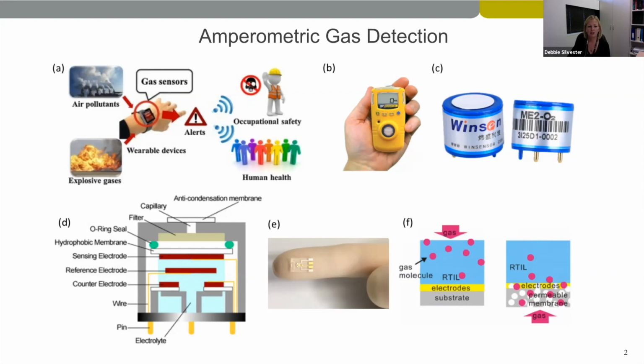So these kind of sensors are based on a 1950s design, and they're very widely used in industry, but they have a couple of drawbacks in that they typically use a fairly high amount of expensive platinum electrode material, so they're very hard to miniaturize, and they also have this liquid electrolyte, which is normally a volatile solvent. So in hot and dry conditions, in particular, the solvent can dry up and then the sensor no longer works.